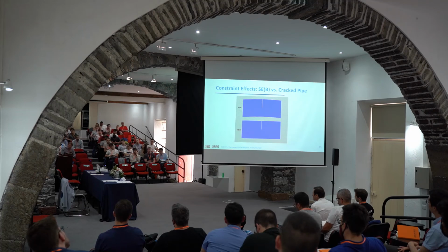Why not use a surface crack with a semi-elliptical flaw? Oh, because it's much more difficult to test. That's one thing. The other thing is, you are right, because the defect in a pipe is actually a surface crack, it's not straight. But then you have to test many combinations of surface crack geometry. That makes it very difficult. But you are not wrong, you're correct.